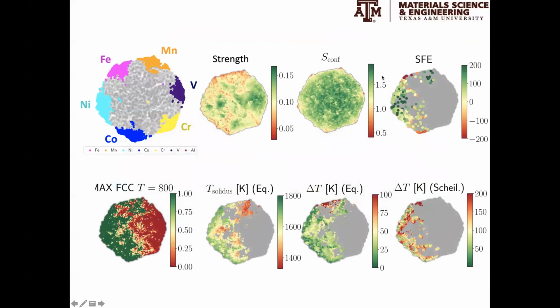Now, when we bring all these things together, including strength — using a strength model that accounts for complexity in the chemistry — and other quantities including stacking fault energy, when we add all these different quantities together, we see that there is not really a very large region where we see green across all criteria.